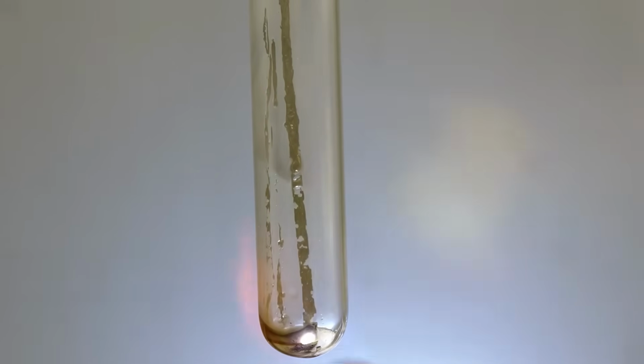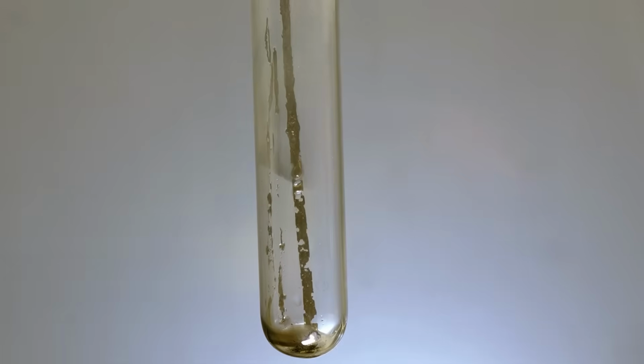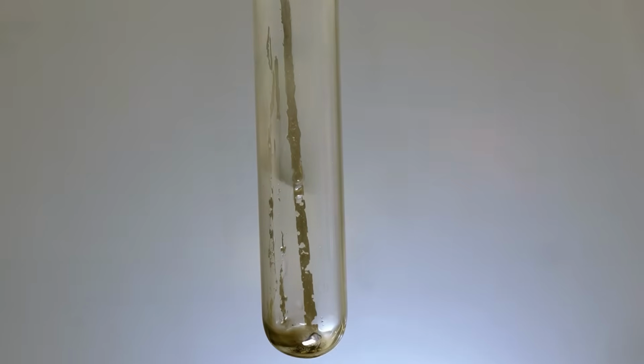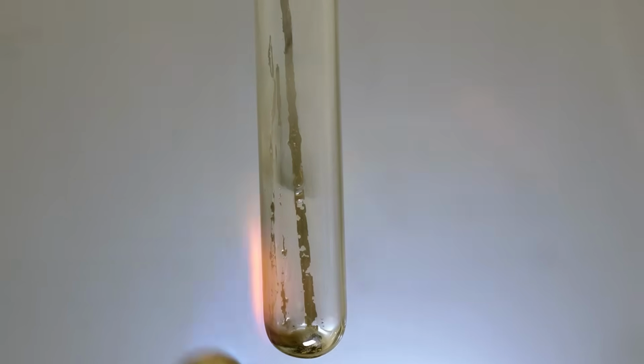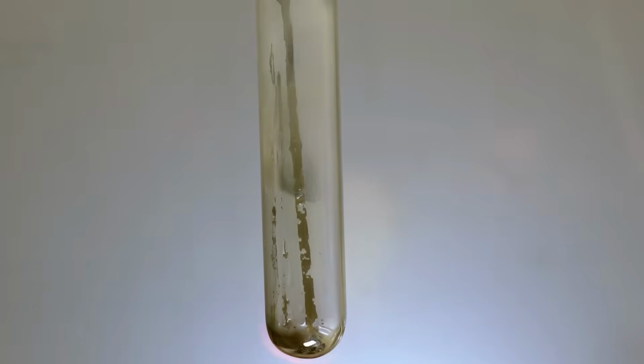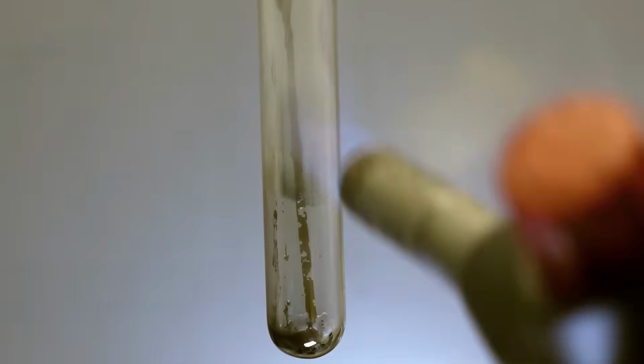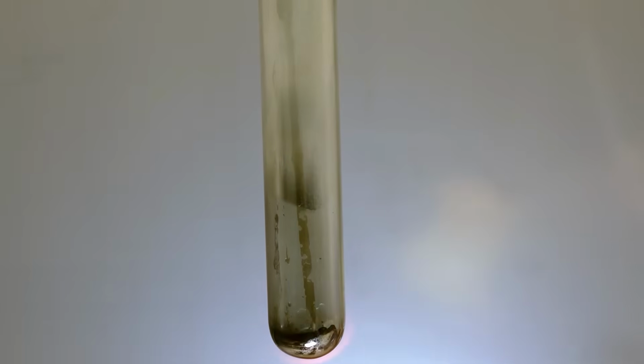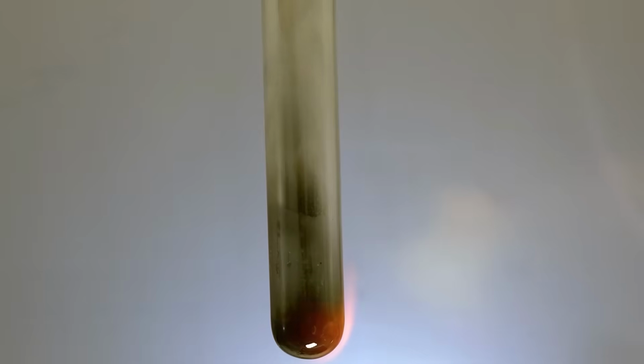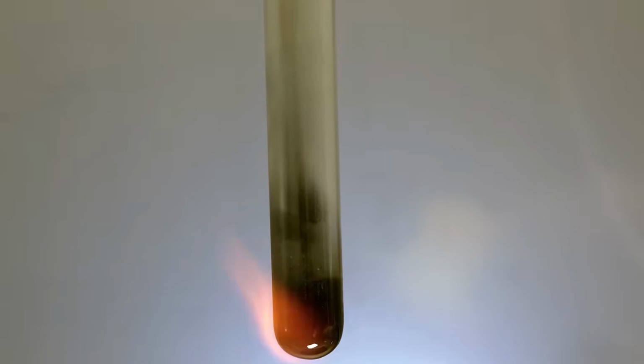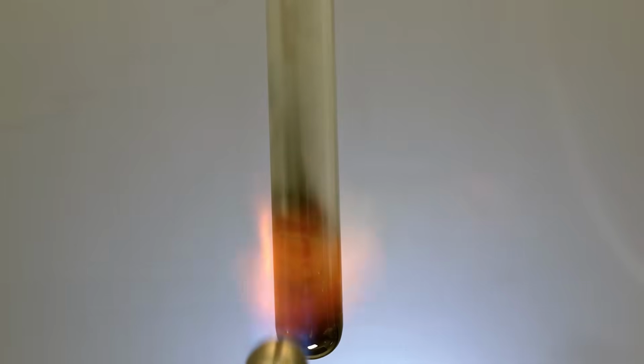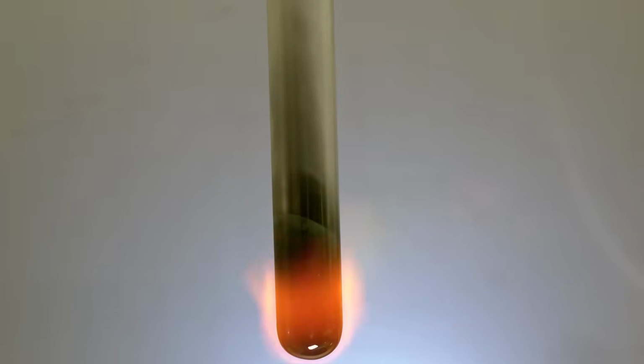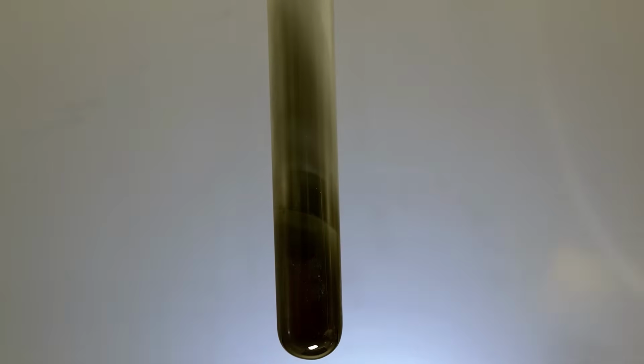With gentle heating, a small amount of golden vapor began to appear in the test tube, which is unusual. With further heating, at 670 degrees Celsius, cesium began to slowly boil, producing vapors of unusual black color. This is quite strange, since in a vacuum the vapor's color was blue. Still, unlike experiments in a vacuum, the black color may indicate some traces of oxygen got into the test tube and oxidized the evaporating cesium.